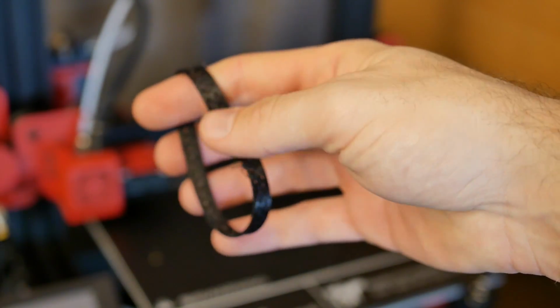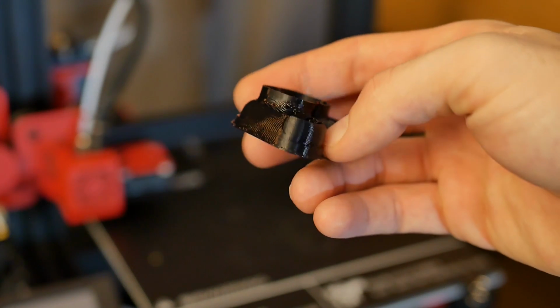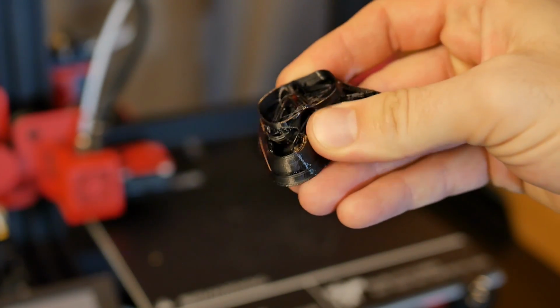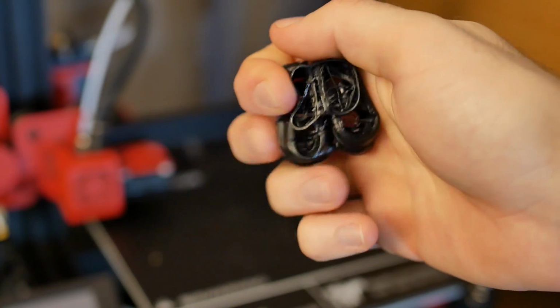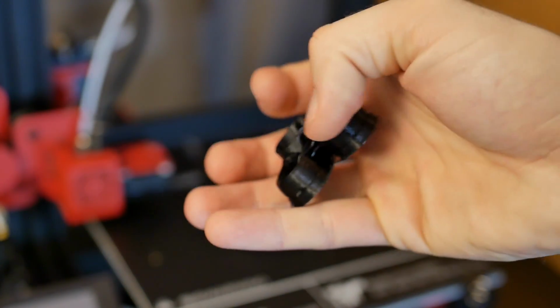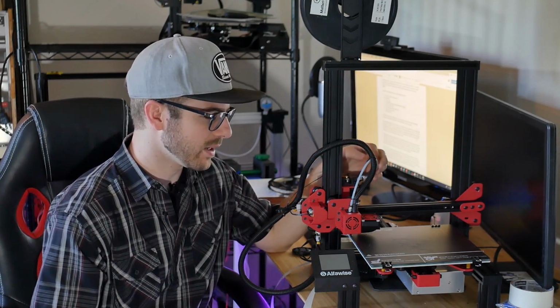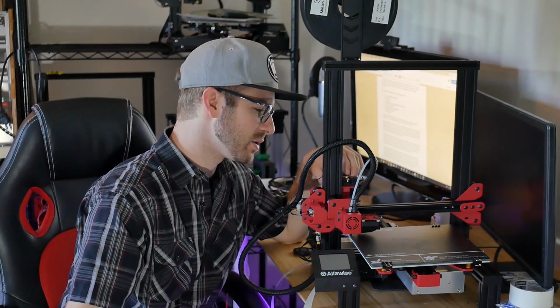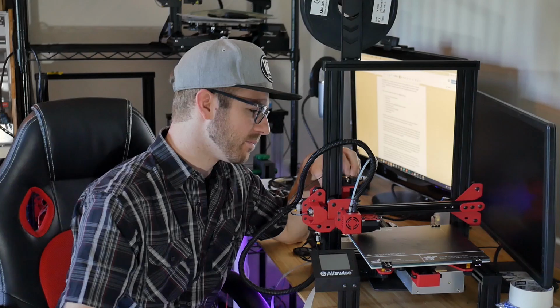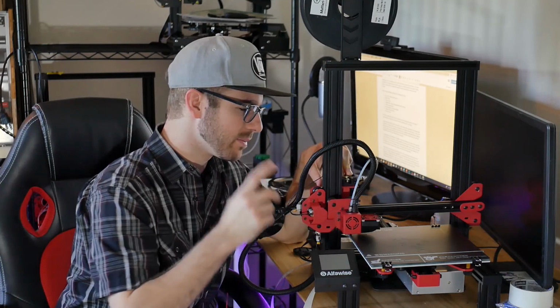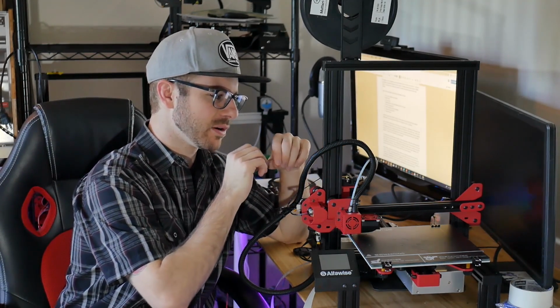I also tried printing out Matter Hacker's 3D fill with this TPU from Sain Smart, and it also was a big failure. So I would say in its default form, the extruder is definitely not set up to be able to do flexibles. I do think that with a slight modification and certainly with an extruder upgrade, you can definitely get away. The Bowden tube length is really short. I was running into issues around the bearing and the gear here, where no matter how slow I was going, even if I got it starting up correctly, at some point it would slowly start to curl a little bit, and then it would just cause a jam. I gave it about 3 or 4 goes before I just said, I wanted to see what it's capable of doing completely stock and not have to modify anything.